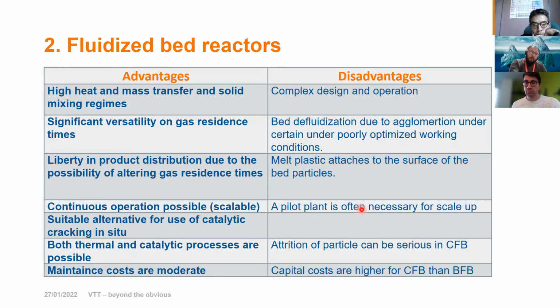In this reactor system, a pilot plant is often necessary for a scale up. You need to have a bigger plant to go for the scaled up plant. Attrition of particles can be serious in CFB, which means that if you have a circulating fluidized bed, then your particles can break very easily, because they are continuously moving from the reactor to the regenerator and then coming back. This movement of the bed can cause particle attrition. They're also on the higher side of the expense, so the capital cost for making a fluidized bed is a bit higher. And in comparison between a bubbling fluidized bed and a circulating fluidized bed, the circulating fluidized bed is also far more expensive than a bubbling fluidized bed.